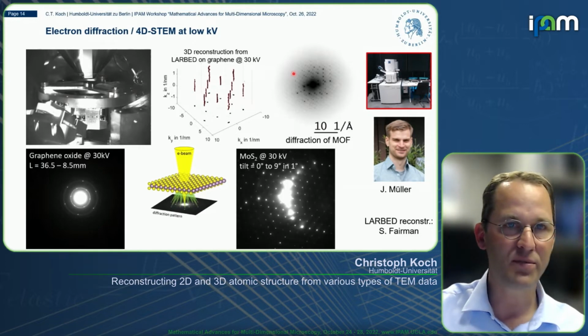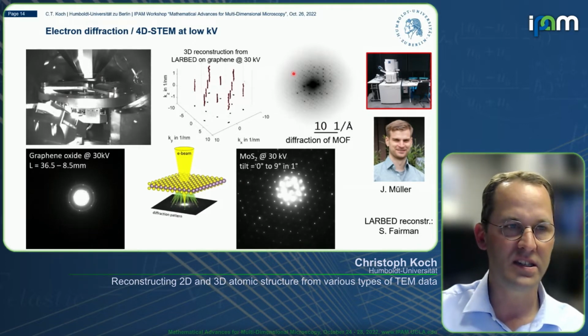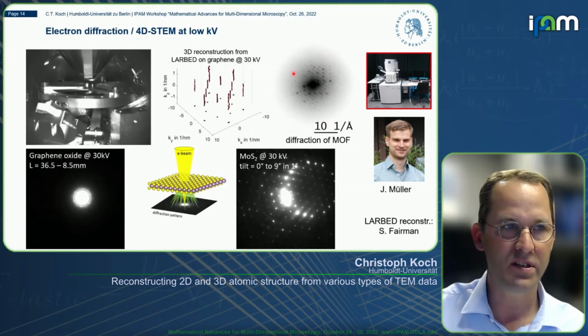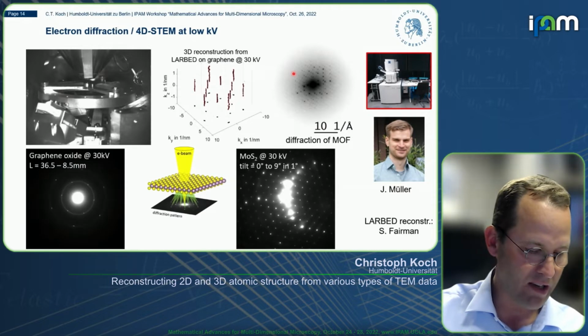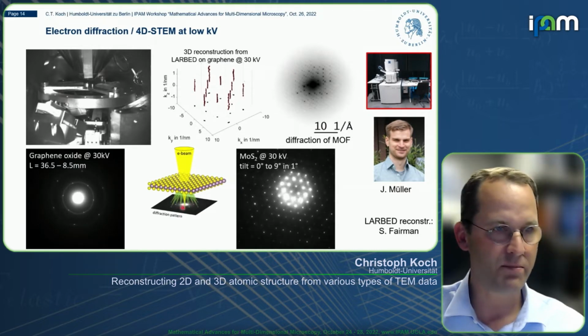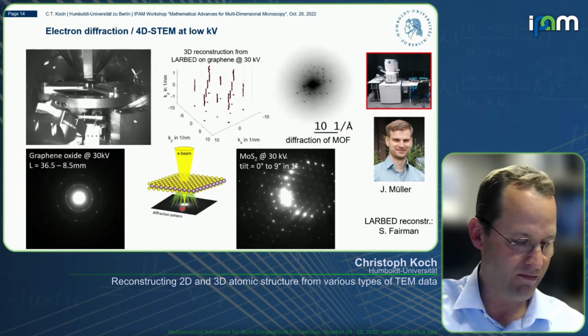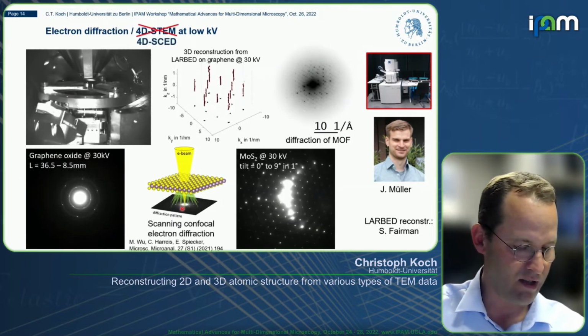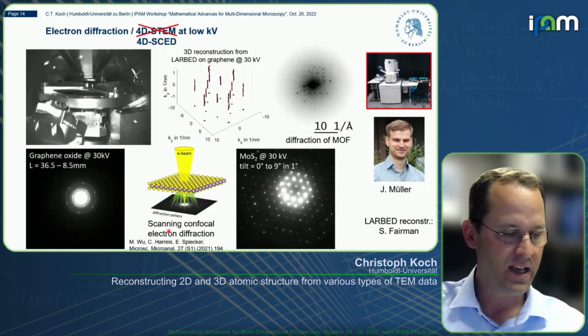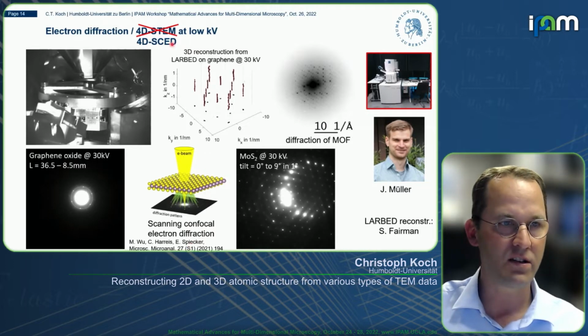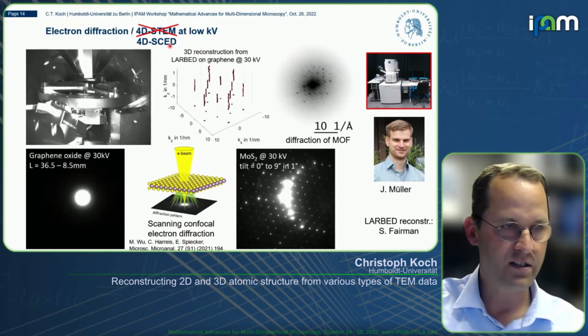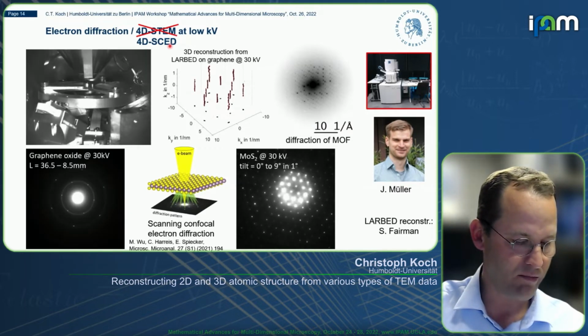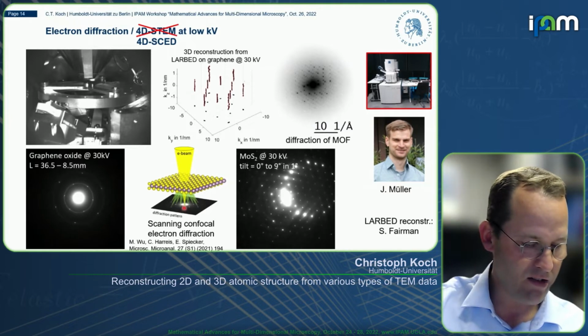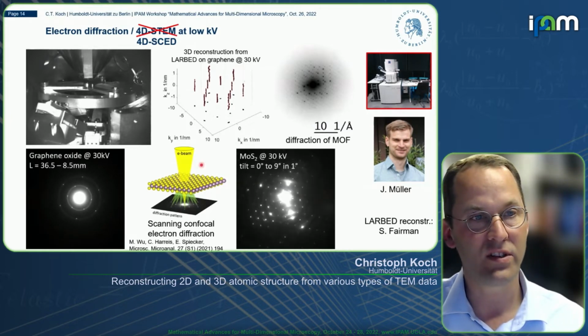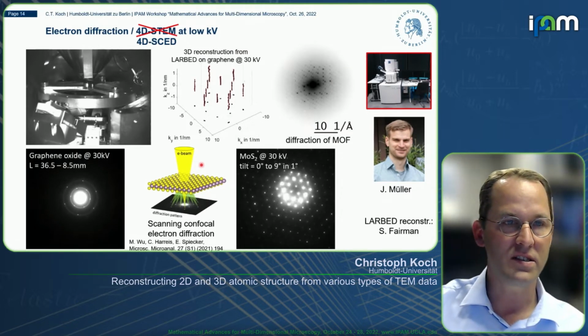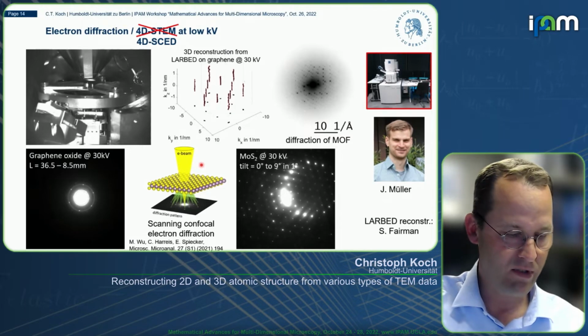And when we now scan across our sample, we get something like 4D STEM information in the TEM, except that maybe the size of the spot on the sample is a bit larger. And if we do a setup like this, that's what we typically do. We focus the diffraction spots on the sample. We probably shouldn't call it 4D STEM. I learned recently that now we are supposed to call this scanning confocal electron diffraction, SCED, very similar to scanning confocal electron microscopy, but in diffraction mapping, because you focus the diffracted beam on the detector and illuminate a larger area on your sample, which, of course, reduces your resolution, but it also reduces the dose on the sample, and that may be advantageous for beam-sensitive materials.